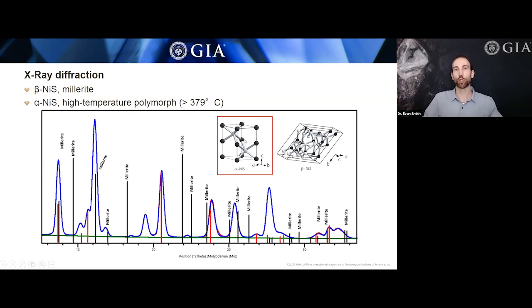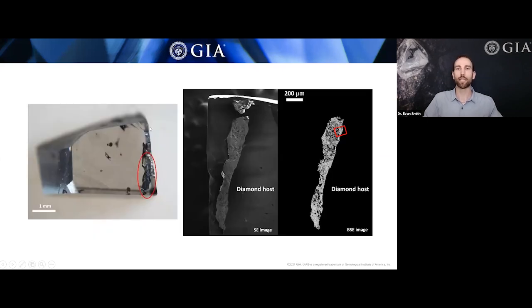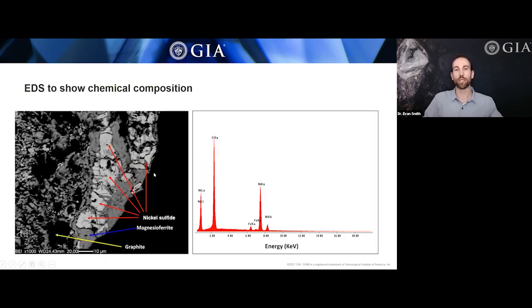The next thing to do was to check its chemical composition, make sure it really is this nickel monosulfide. So here's the sample again. It's been cut down to isolate this one little part of the inclusion. And we're looking at it more close up now in a scanning electron microscope. This is just part of that altered inclusion. And we're going to zoom right in on this little red box here and use a technique called EDS, energy dispersive X-ray spectroscopy, to see what chemical elements are present. So here's that zoomed in region here.